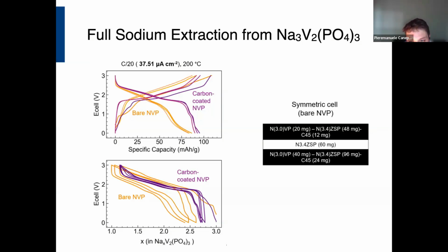We have been cycling some of these batteries. These are all Nasicon batteries, the Oreo battery that I've been showing you. These are really preliminary data because it's difficult to optimize this material, but it's important to see that there is a lot of optimization that needs to be done if we want to really have this battery prototype work. I don't think they are useful from a standpoint of energy storage because they are cycling at high temperature, as you can see, 200 degrees Celsius, and the capacity that you can extract is very limited. But certainly, I show you some interesting results on the sodium vanadium phosphate that can be used in traditional liquid type batteries, right? And with our carbon and more commercial solid liquid electrolytes.